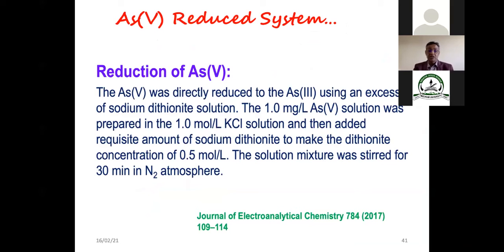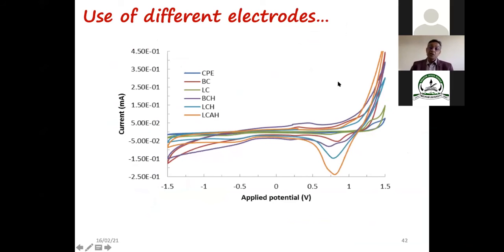The other system that we tried for arsenic 5 was published in the Journal of Electroanalytical Chemistry. We reduced the arsenic chemically, using sodium dithionite, to reduce arsenic 5 to arsenic 3, and then we detected this arsenic 3. The results are slightly different. You see there is no peak on this side, the oxidation peak we are not getting, but on the lower side you can see the reduction peak that we get.